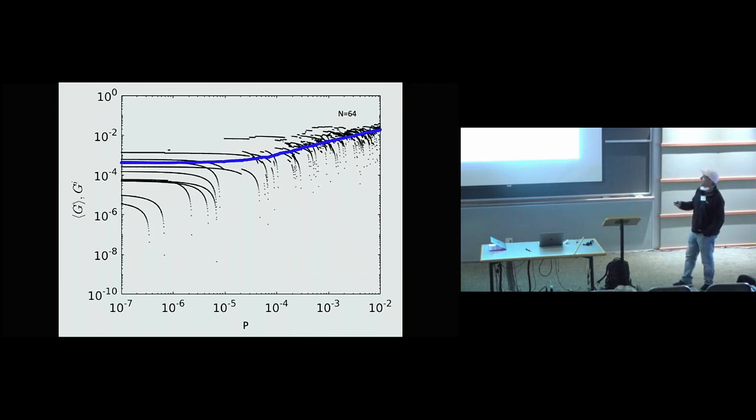The ensemble average data looks like maybe what you would expect. As the pressure increases, the contact number is increasing, the material is strengthening. But if you look at any individual configuration, it's doing the complete opposite. It goes down because of the effect I just talked about, and then there can be a rearrangement, and it'll rearrange to a new configuration. The very interesting thing is that these shear moduli can go negative.